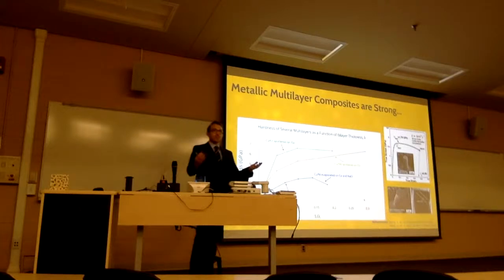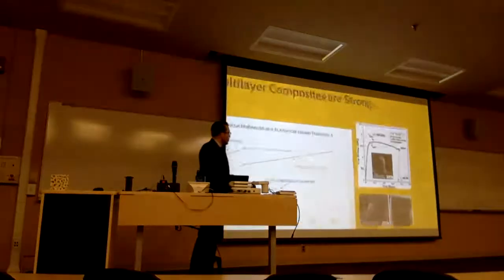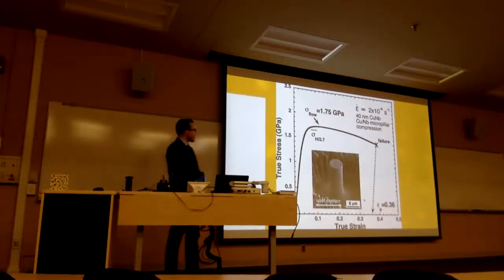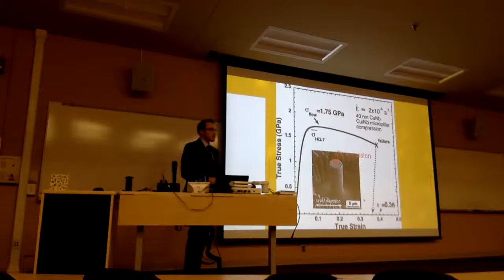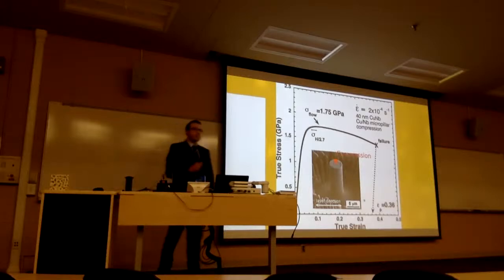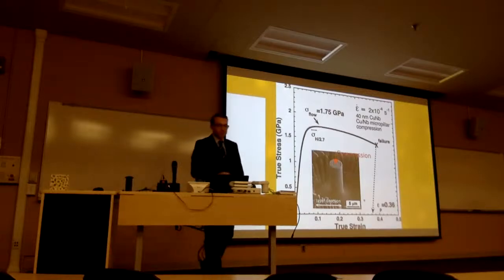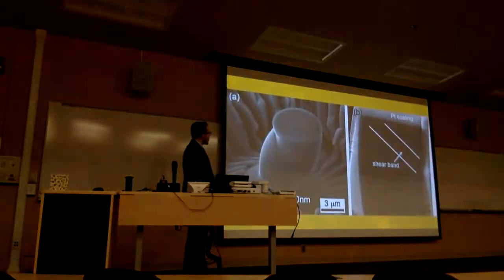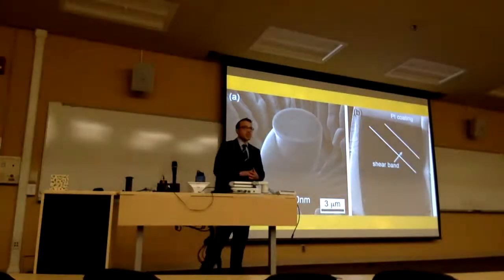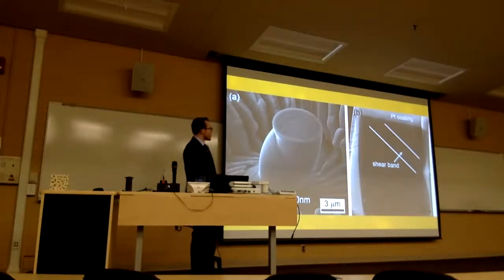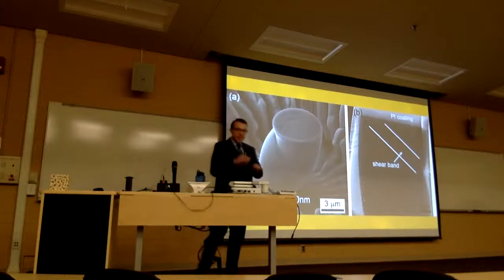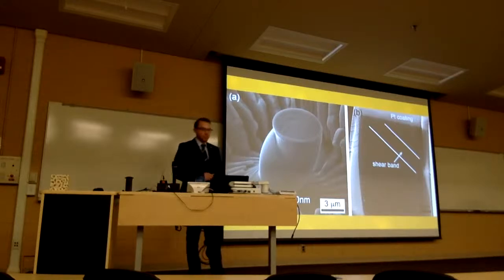So you might be thinking, well, that's great. We have ultra high strength in a material. So what's the problem? Well, if we load this sample up in compression, so we make this micropillar and compress it down, deform it, it actually has these ultra high strengths, but it fails very suddenly like a brittle material. And the reason for that is this is the post-deformation sample. We can see that the plastic flow that we've created during deformation localizes into a single region in the sample known as a shear band. And that material fails very suddenly like a brittle material.